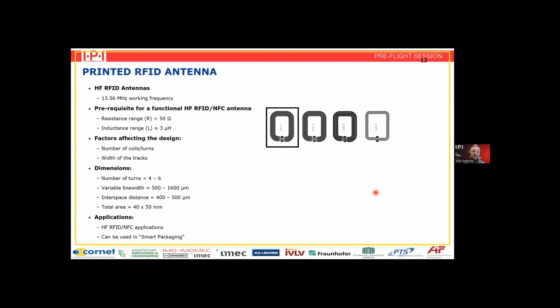Then of course you go towards the printing of the devices, and here we print RFID antennas. We have a working frequency of 13.56 megahertz, and then of course some requisites that we needed, the resistance range and the inductance range, to be operational with the RFID provided by IMEC. We had a design phase, where we looked at the number of coils or the number of turns, the width of the tracks, and also, for example, the line width, the interspacing between them, and the total area, and that was investigated onto the substrate.